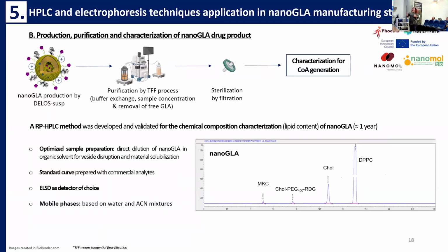And after this, our partners, Nanomol Technologies, produced these liposomal-based formulations entrapping the enzyme, purified them by tangential flow filtration in order to remove all the free GLA, and sterilized them. And we analyzed the most critical parameters, which is the analysis of chemical composition in terms of lipid content of this.